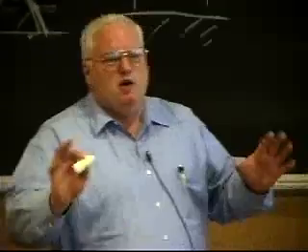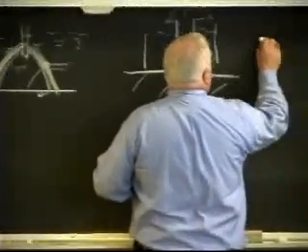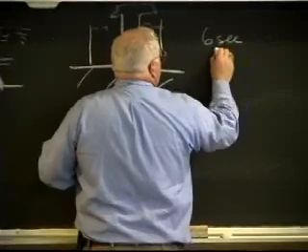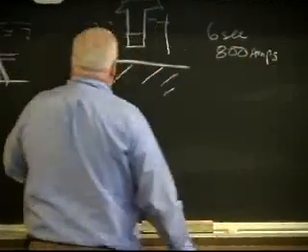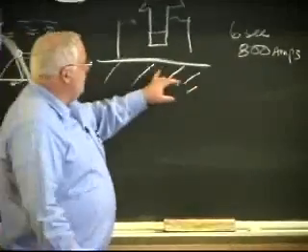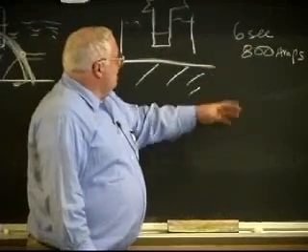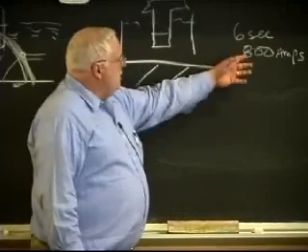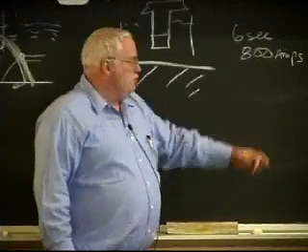And I said, no, we don't want to do this at 2,000 amps. We want to do this for 6 seconds at 800 amps. They were trying to do everything really fast at high currents. They were doing 1.5 seconds at 2,000 amps. And I said, well, let's do it at longer time, lower current, because that's going to cut down on my plasma jet. That's more like submerged arc welding.